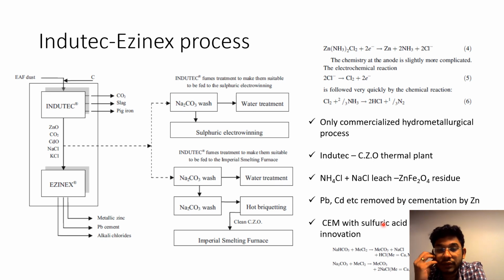So they had to solve this issue, and then they came up with two different solutions. One solution for Ezinex was this. They took the leach solution and they had it in the catholytic chamber, and then they used a cation exchange membrane, and they had an electrochemical reactor with 2 chambers, and instead of chlorine evolution in the anolytic compartment, they just filled it with sulfuric acid, and then they let oxygen evolve from sulfuric acid. That's a really nice solution.